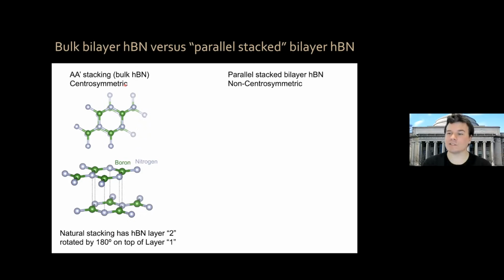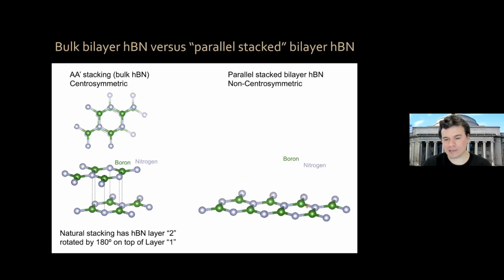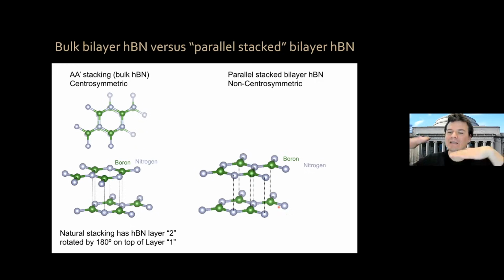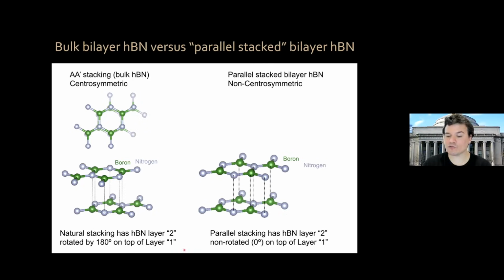Now, since we can place two-dimensional materials on top of each other arbitrarily, we can do something, which is we can make a highly non-equilibrium hexagonal boron nitride bilayer. What do I mean? I mean the following. Let's take a monolayer of hexagonal boron nitride. And now I put here, as a guide to the eyes, each of the atoms, boron and nitrogen. And now let me split it in two and parallel stack it on top of itself, okay? Meaning, let's put hBN layer 2, non-rotated, so 0 degrees alignment, on top of layer 1. Now we have nitrogen atoms on top of nitrogen atoms, boron atoms on top of boron atoms. That's extremely uncomfortable for the system.